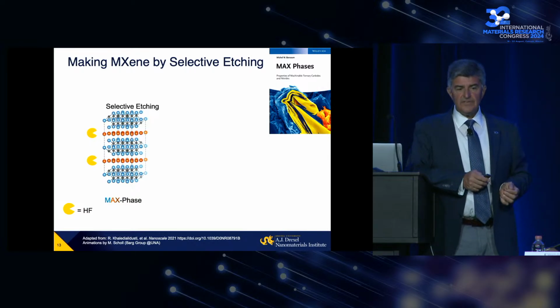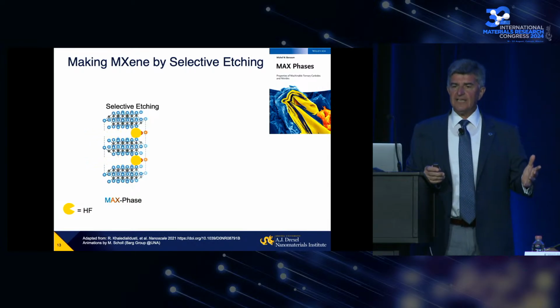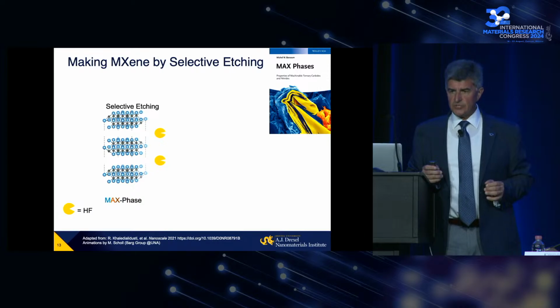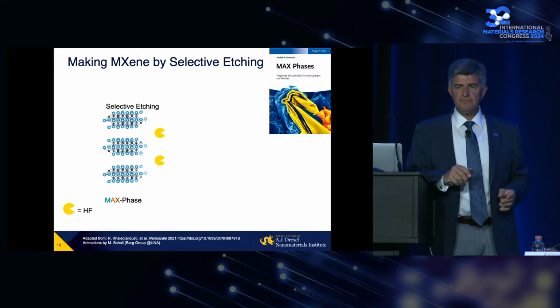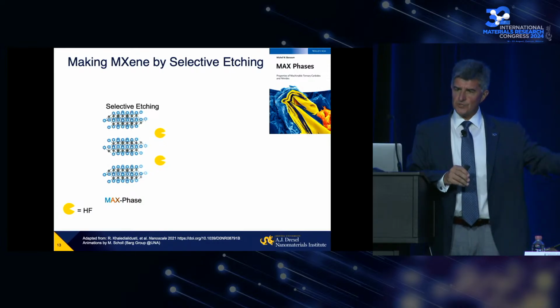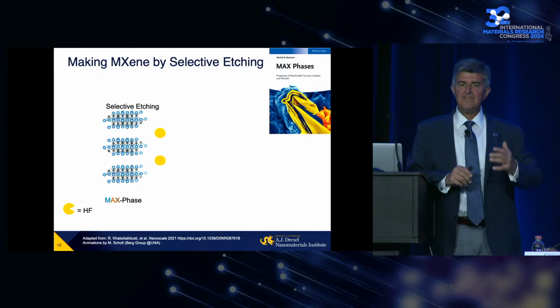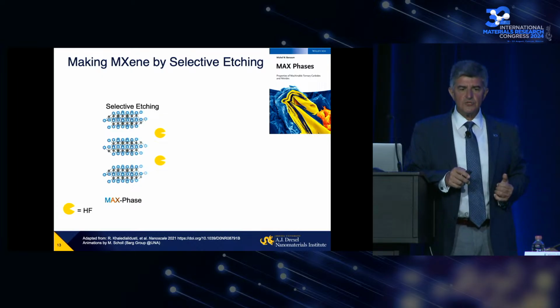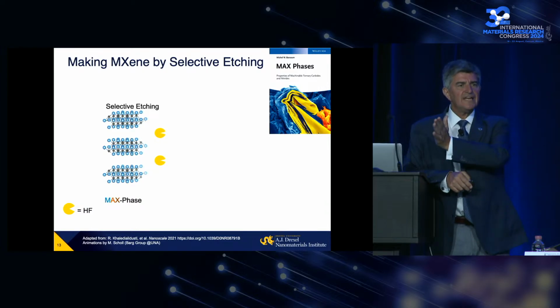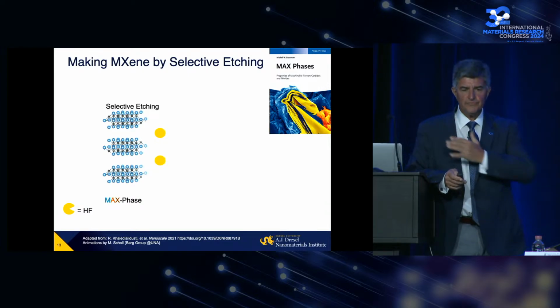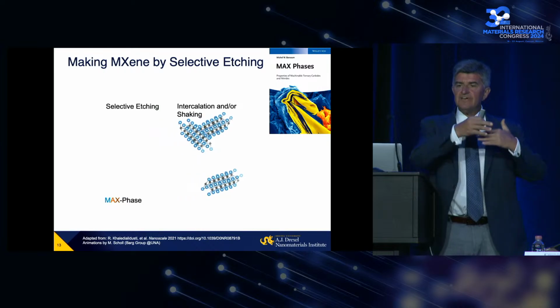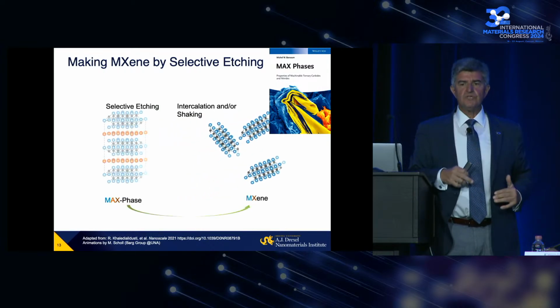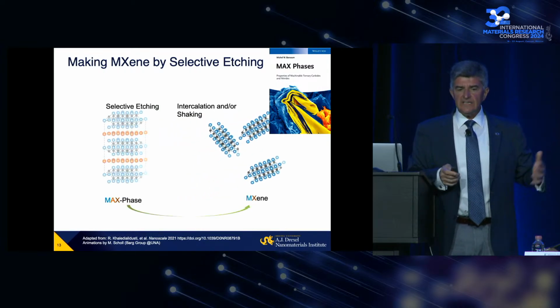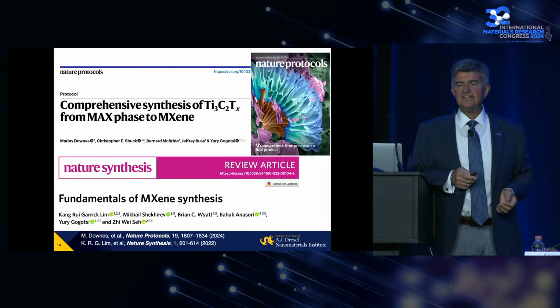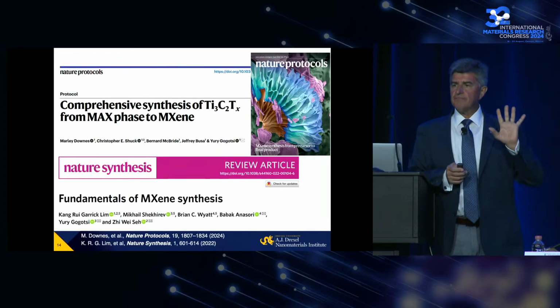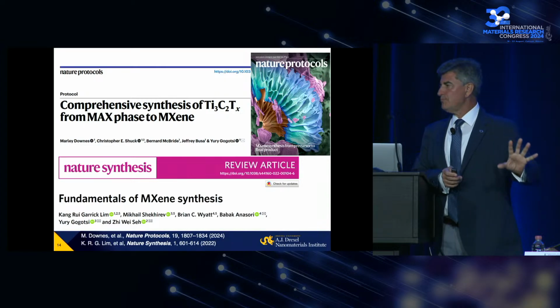What we did - we used electrochemical, just chemical etching, selective etching techniques that I've been exploring for 30 years, initially to make carbon materials, and now to etch carbides and nitrides to remove monatomic layers of elements like aluminum. Then we have weak van der Waals or hydrogen bonding between the layers, so we can easily intercalate and separate them, like other materials.